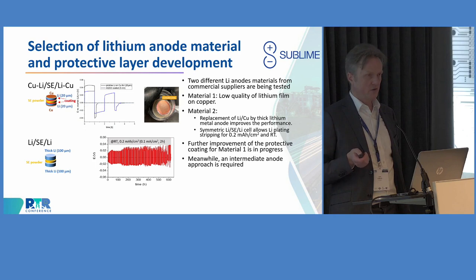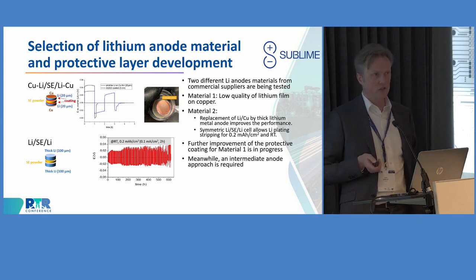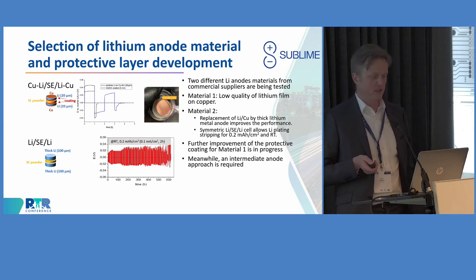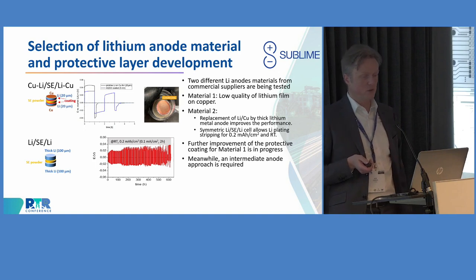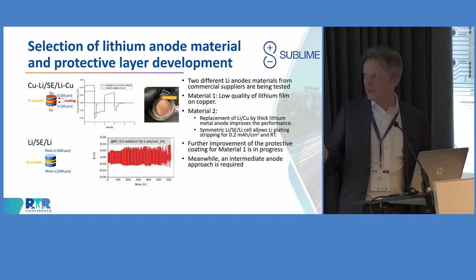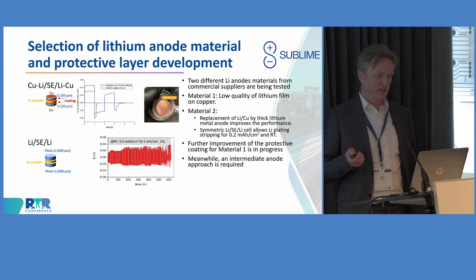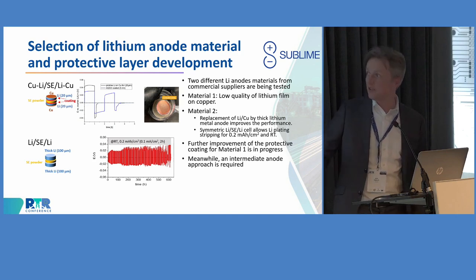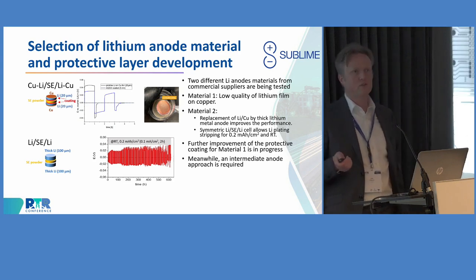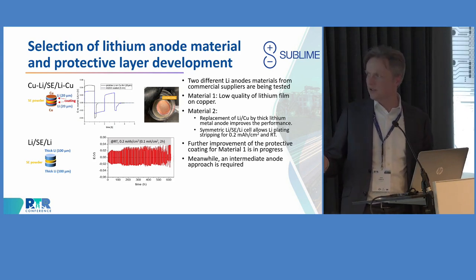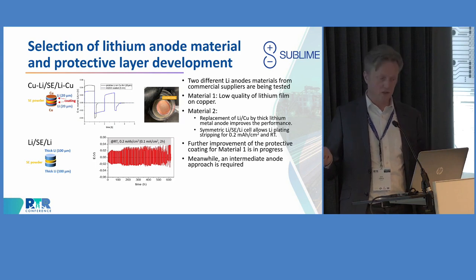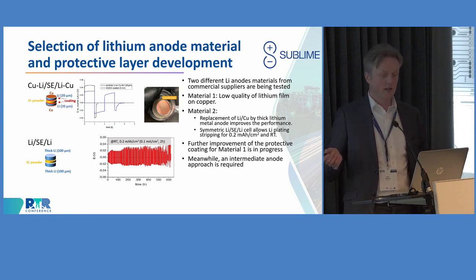So cycling of these things, especially also with the development and the purification of the protective layers, showed us that we, at the moment, not yet with that material, are able to cycle as many times as we like. You see here these diagrams of charge and discharge, and you see this is then at the end very quickly destroying the cell. If we use different kinds of materials with thicker lithium, we see that our approach actually is going to work, so we can cycle quite a lot of times.